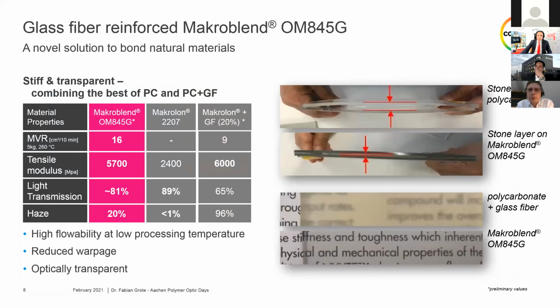However, how to make that possible is not so straightforward. If you look on the right-hand side on the top image, you see a standard polycarbonate injection molded onto a stone veneer layer. And you see how the material starts to bend, which is not an issue normally for polycarbonate, but this natural material has a tendency to bend. And that can be overcome when utilizing glass fibers. This is what you see on the second image on the right from the top.